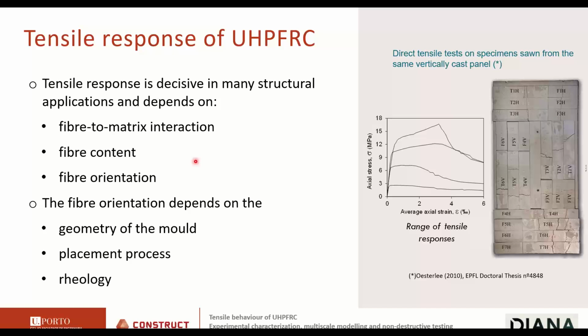So tensile response is decisive in many structural applications and depends on the fiber to matrix interaction. So the way we develop the mix design can be tailored to get the behavior that we want. It depends on the fiber content, which of course can also be tailored in the mix design, but also depends on the fiber orientation, as we have seen. But the fiber orientation depends on external factors that we cannot control when we are designing the mix. So it depends on the geometry of the mold, on the placement process, and on the rheology of the material in the fresh state. Some evidence here taken from the bibliography.